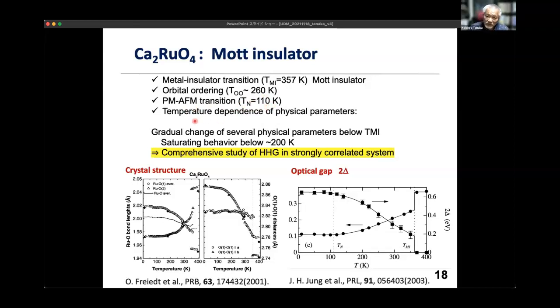But the important point of this material is that below this metal insulator transition, the lattice is changing, and anisotropy is increasing at low temperatures. If you look at the lattice constant, some bonding length is increasing, but in the other direction nothing happens, so anisotropy is increasing. But the system's crystal symmetry is unchanged. The interesting thing is that the optical gap is changed very largely. This is the metal insulator point, and the bandgap energy is around 0.2 eV around room temperature, but at low temperature it goes to 0.6. So a 3 times opening occurs.